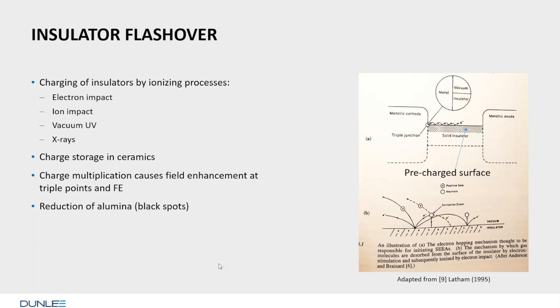Now we have not only vacuum in the tube, we have also insulators. And here you see what an insulator does when it's subject to electric force. There's a tricky point in an insulator metal combination, the so-called triple point. This triple junction here connects vacuum, an insulator, and the metal. The insulator wants to get rid of its electric field due to its dielectric constant. It pushes the electric field aside, and if you have a little void here or some irregularity, the electric field is enhanced here and creates field emission.